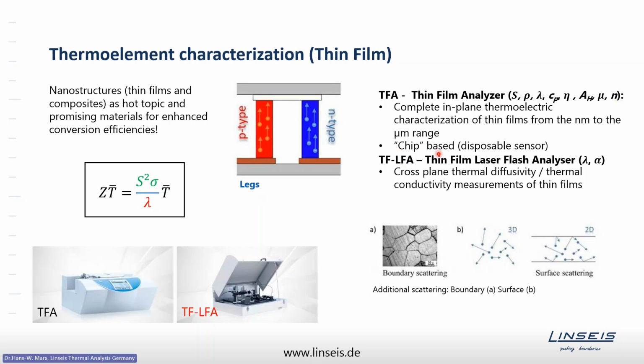The thin film laser flash analyzer is an instrument dedicated to measure thermal conductivity and thermal diffusivity. These methods distinguish each other by the direction of the measurement. In the thin film analyzer, all properties are measured in the plane of the thin film, while for the thin film laser flash analyzer, the thermal diffusivity and conductivity are measured across the plane of the thin film.